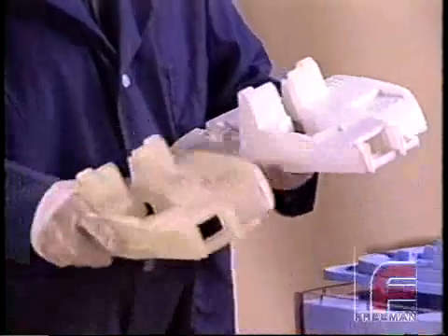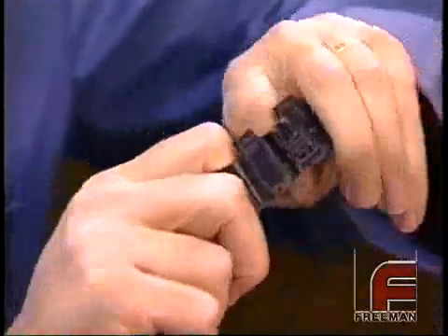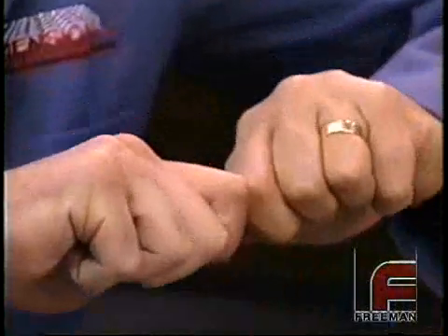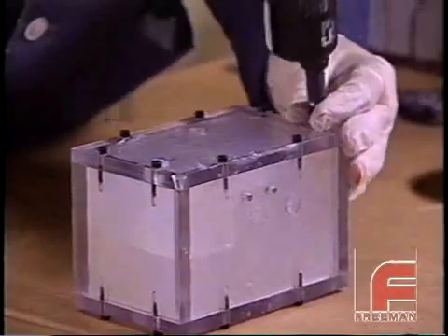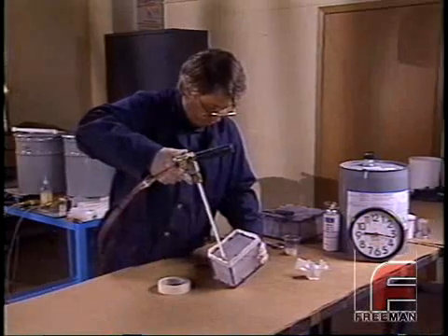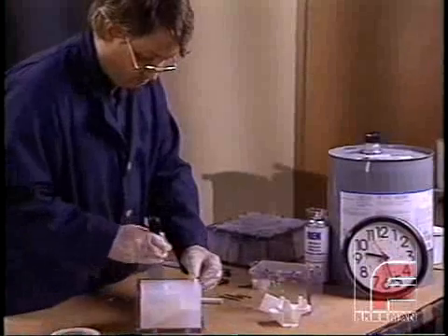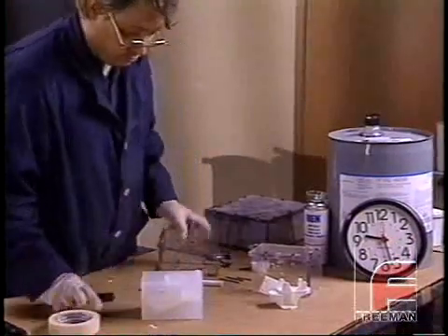In the past, urethane materials may snap, but they don't snap very often or very well. And that isn't representative of what the customer is going to get out of his parts when he goes to production. High heat deflection temperature, of course, was also a very major requirement, especially with Harley-Davidson, because of their enthusiasm for testing the parts on the bikes. We had some early difficulties with other resins because we had managed to get the high heat deflection temperature, but the parts were too brittle. Ciba's RP6452 material allows us to make ABS-like parts that have high impact, that have good snap fits, and represent parts that the client is going to get when he goes to production.